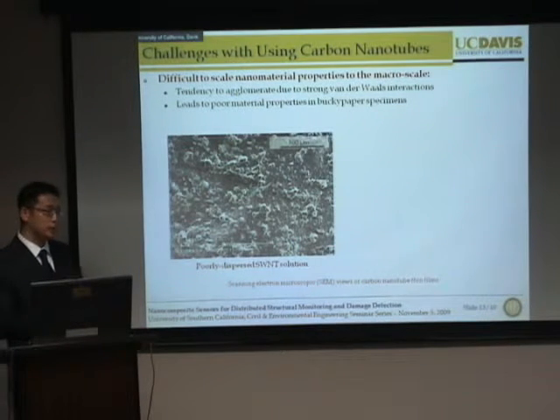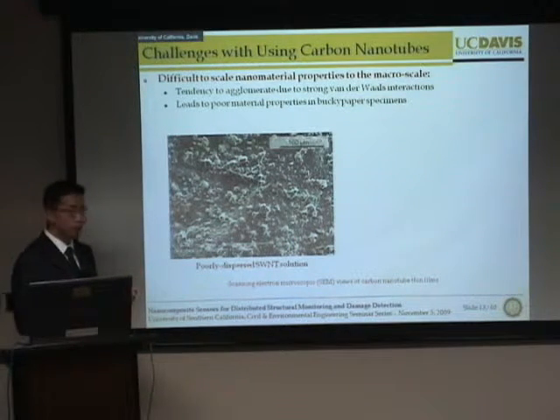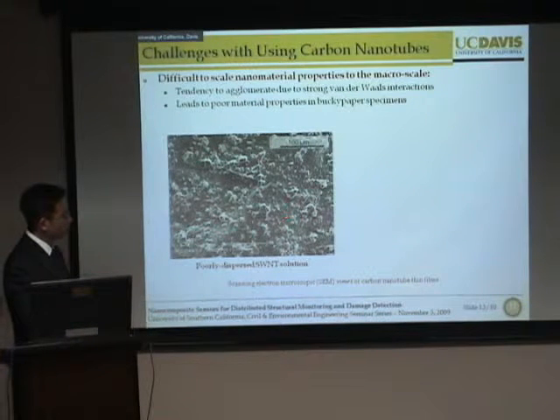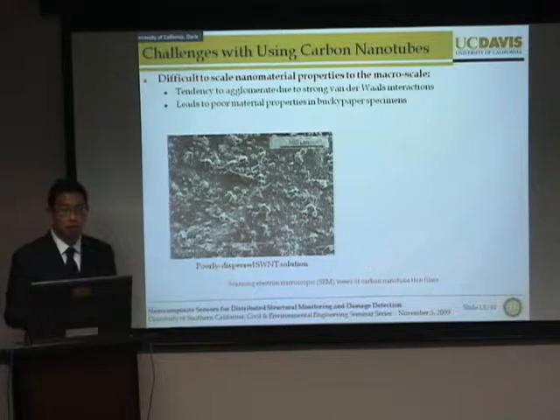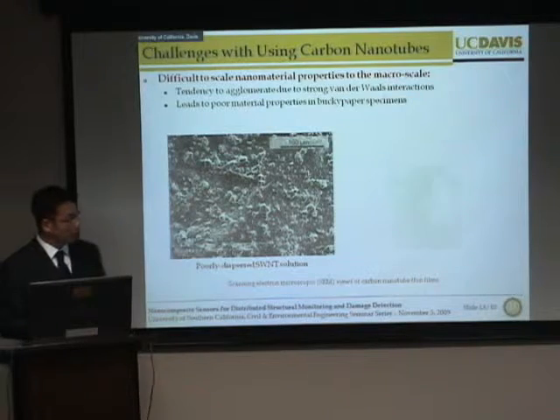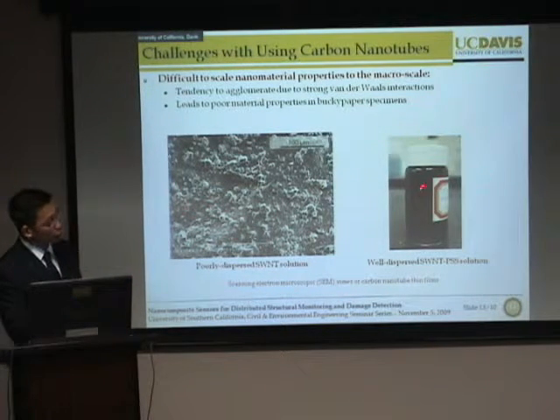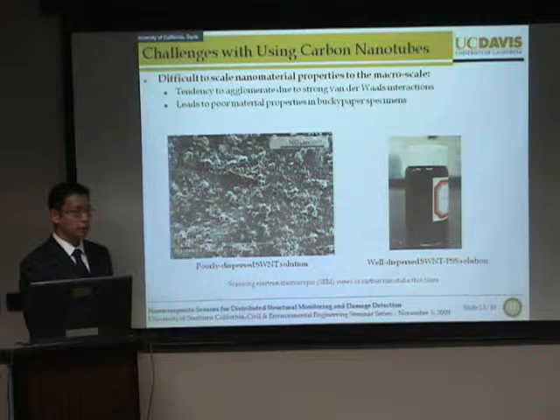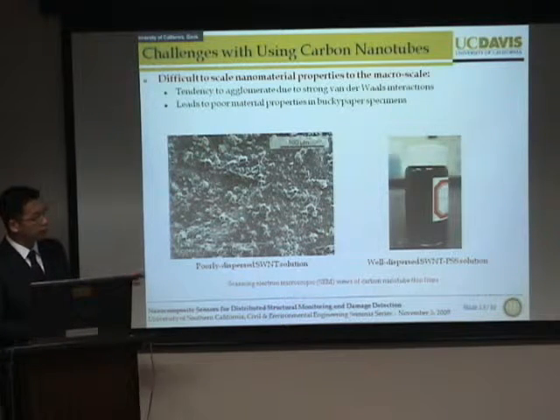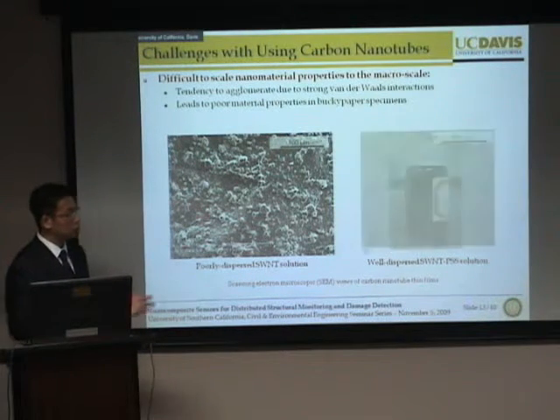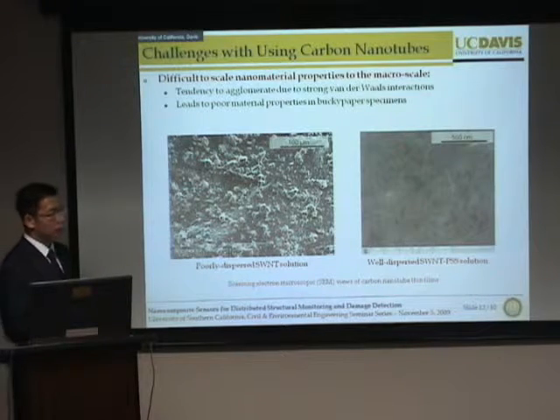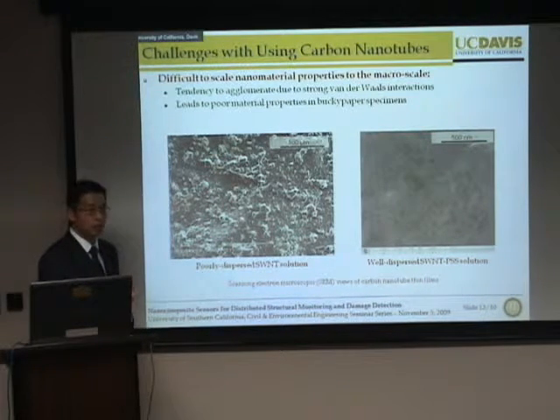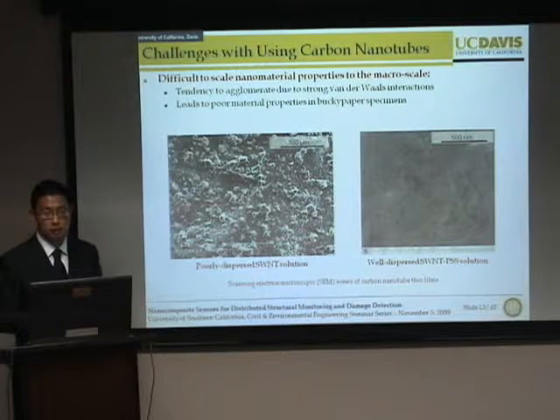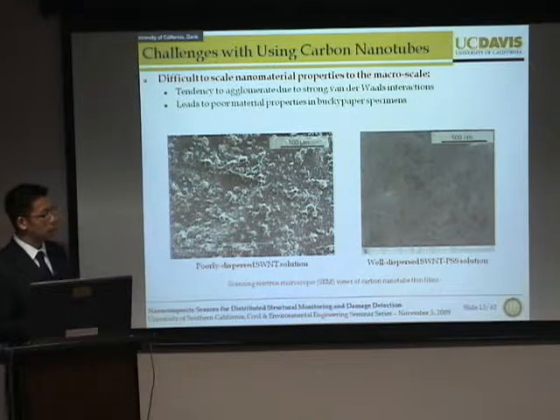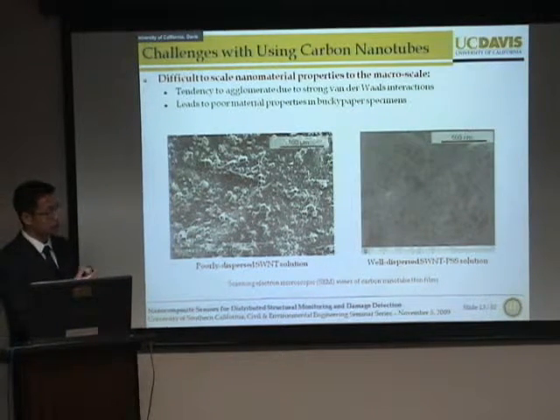So if you consider the case when you mix carbon nanotubes into another liquid, what we obtain is a two-phase system as shown. Obviously, the carbon nanotubes are clumped together and precipitated to the bottom. And if we directly use that two-phase solution to create a thin film material, we end up getting a highly inhomogeneous thin film due to this lack of control. On the other hand, if we're able to disperse individual carbon nanotubes in solution, we can create a more homogeneous film characterized by a dense percolated structure of individual or small bundles of carbon nanotubes. This percolated structure will become important later in my discussion.